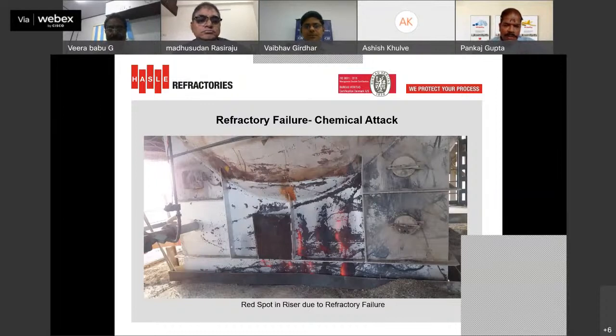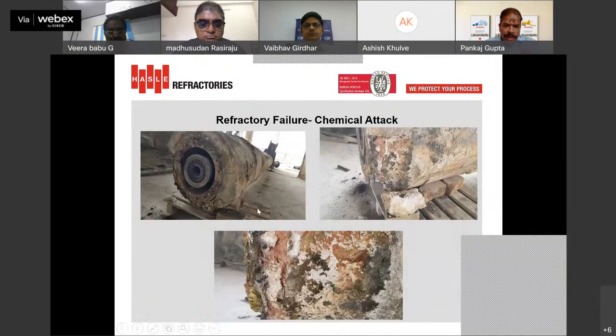So this is the picture from one of the risers where the refractory of a riser area is attacked by high alkalis and chlorides. The refractory failed within 6-7 months, and the red spot appeared. This is the picture of a burner pipe where 100% petcoke is used, and the refractory is attacked by high sulfur content, and this castable failed within 3-4 months.